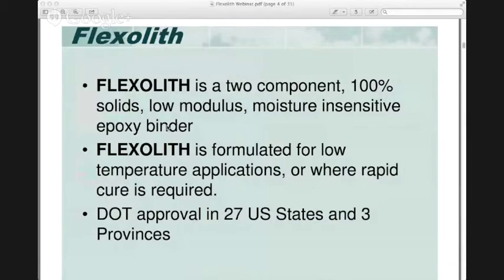FLEXOLITH is the product we're talking about, which is a 100% solids, 2-component, low modulus, moisture insensitive epoxy binder. The moisture insensitivity is important here as well, because we can't always dry out these structures 100%. So we need something that has some moisture tolerance. It is formulated for low temperature applications, which allows for either a quick turnaround time, or you can use it down into the 4 or 5 degrees Celsius range. Currently, 27 state DOTs in the U.S. approve this product and have it on the approved products list. We have 3 provinces, as well as some special provisions which allow some localities to use this material, but it may not be in their day-to-day specifications, but it has been used in numerous other locations as well. Next slide.